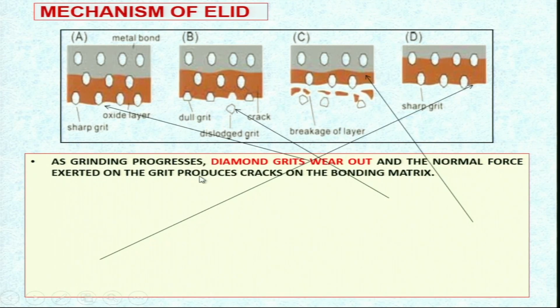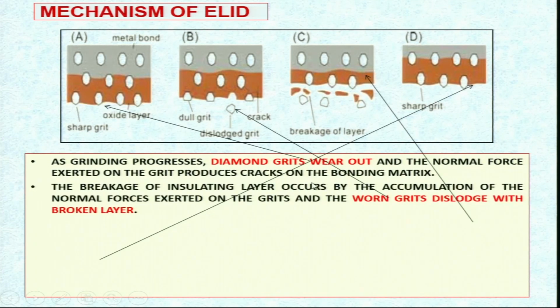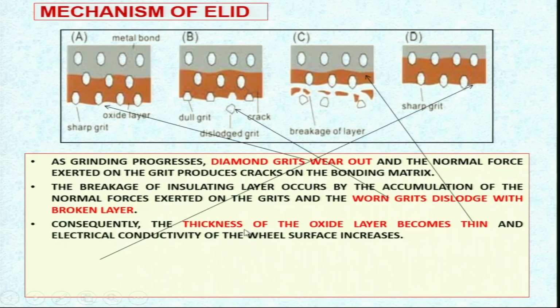As the grinding process progresses, diamond grits wear out, and the normal force exerted on the grit produces cracks on the bonding matrix. The breakage of the insulating layer occurs by the accumulation of the normal forces exerted on the grits. This is the insulating oxide layer which has been formed, and the worn grits dislodge with the broken layer. Both of them are separating out from the grinding wheel. Consequently, the thickness of the oxide layer becomes thin. You can see this is thinner compared to the oxide layer over here, and the electrical conductivity of the wheel surface increases because part of the non-conducting layer has been removed.